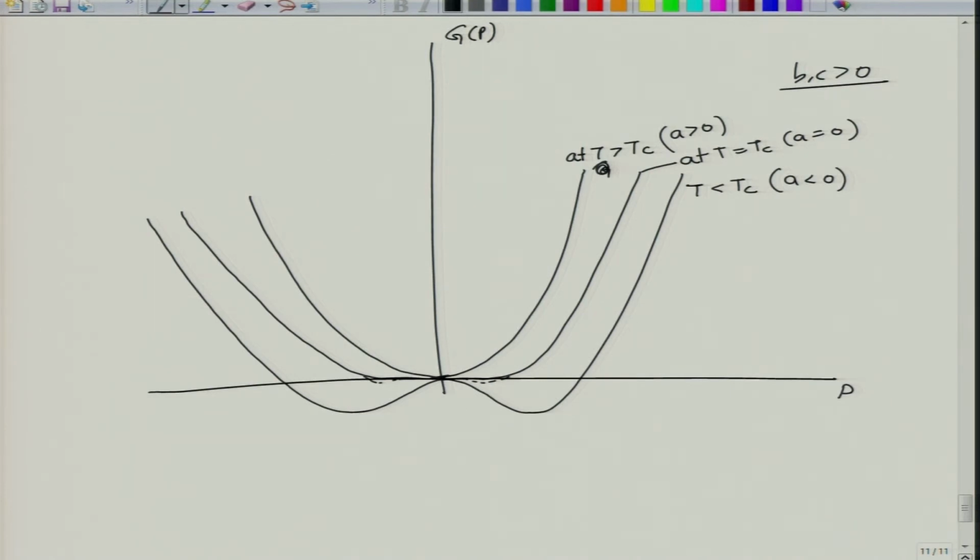So, this is reflected in terms of polarization. If you plot polarization as a function of temperature, the polarization decreases gradually to zero at a temperature called Tc. So, below Tc you have finite polarization, either you will have plus P or minus P, it is a uniaxial ferroelectric and both the states are equal. So, you can write this as mod P.